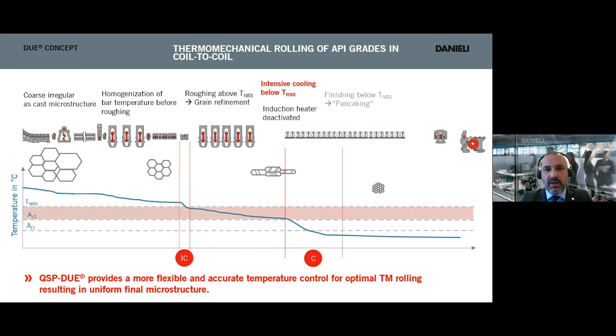But in order to highlight the flexibility of the plant, on the same line pipeline grades for thicker products can also be made, starting from the coarse irregular grain size of the as-cast microstructure. We can get an optimization through the high reduction stands before reducing the temperature thanks to the intensive cooling system at the finishing mill entry side, in order to bring the temperature below the no-recrystallization temperature, and generating in the finishing mill a pancaking effect that, coupled with the proper cooling strategy at the runout table, allows accurate temperature control, and so to perform real thermomechanical rolling